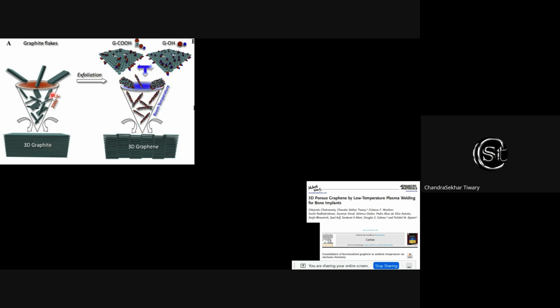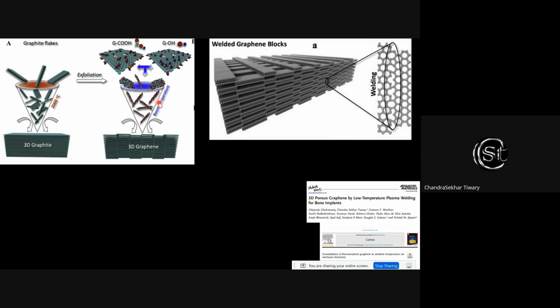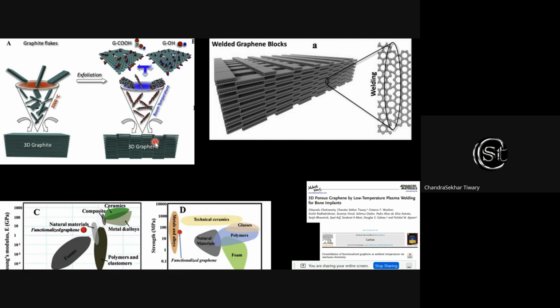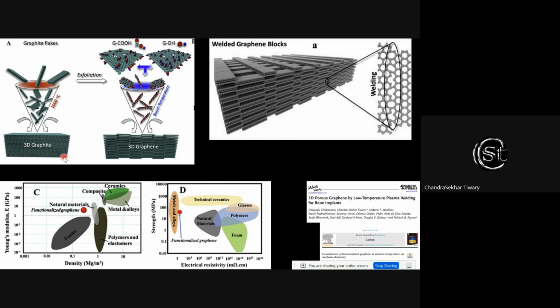So what we did, we took graphene, functionalized it with COOH or OH functional groups, mixed them together at room temperature and compacted them. When you do that, we can make a nicely welded structure of 3D graphene, which has properties very similar to graphite, and also it has ductility, which is not there in graphite. Bulk graphite breaks in a small bending, and if you know about graphite, handling it is very difficult because it is very brittle. A small impact breaks it. But the structure made of graphene has enough ductility to take some of those shock loads.